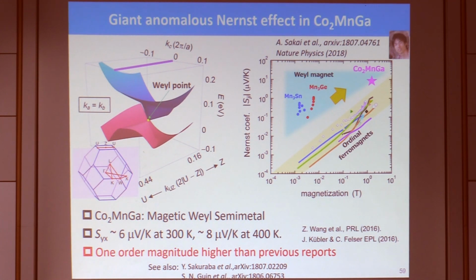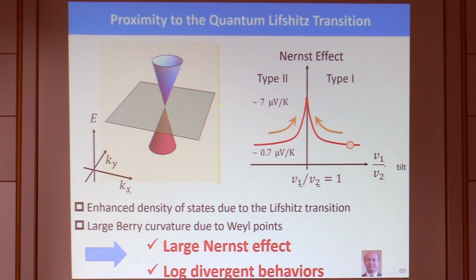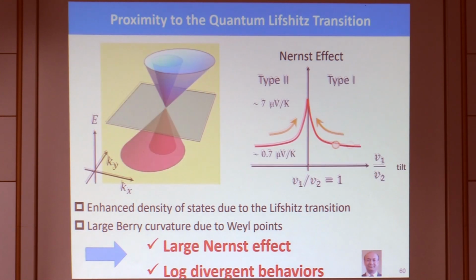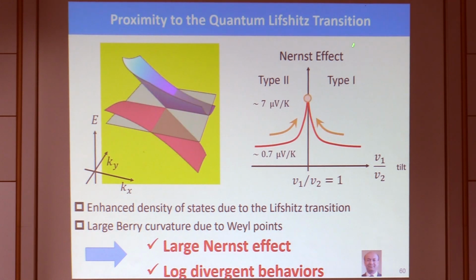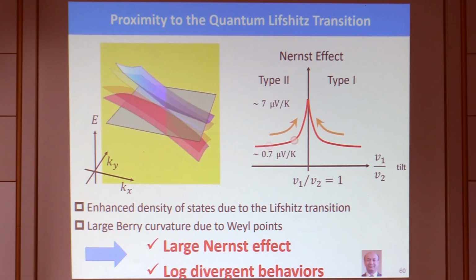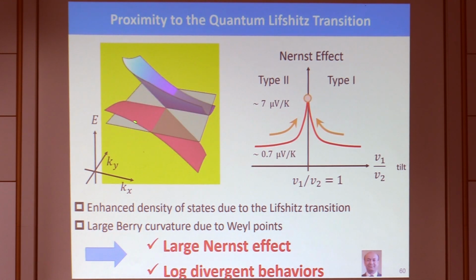Here is the mechanism for why it is so much enhanced. This material is not simply a magnetic Weyl semimetal, but is actually located very close to what is known as a quantum Lifshitz transition, separating type 1 and type 2. Exactly around this quantum Lifshitz transition, the band dispersion is very, very flat. So the key here is that you need to enhance the density of states of the band that creates the large Berry curvature, the one that has the Weyl point. This is what is actually happening and is realized in this material.